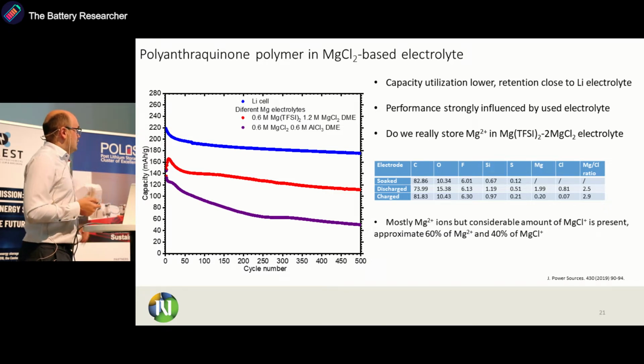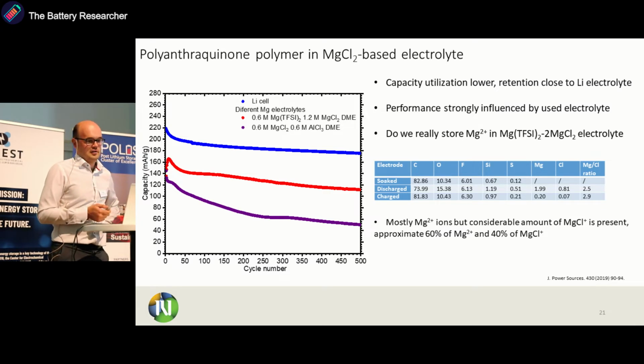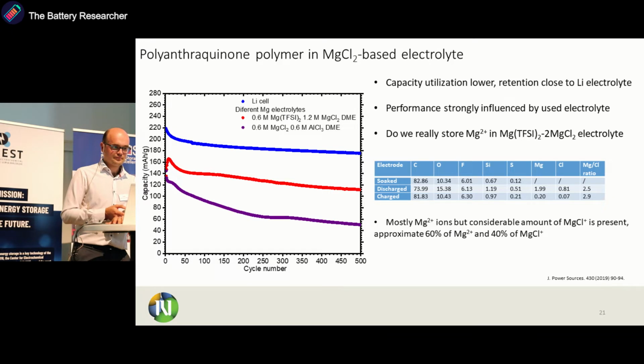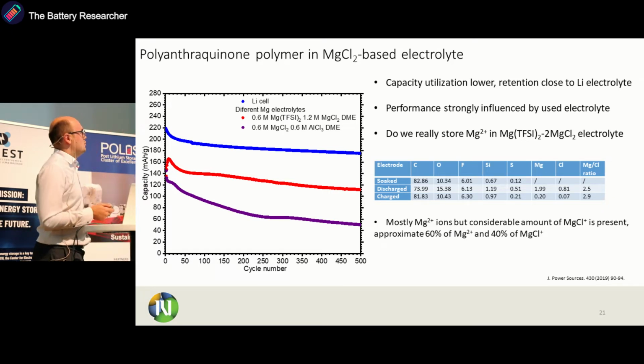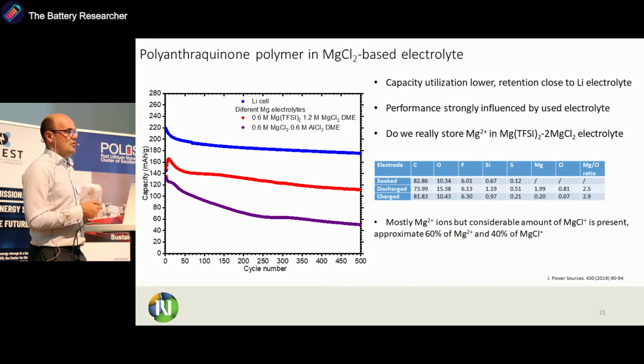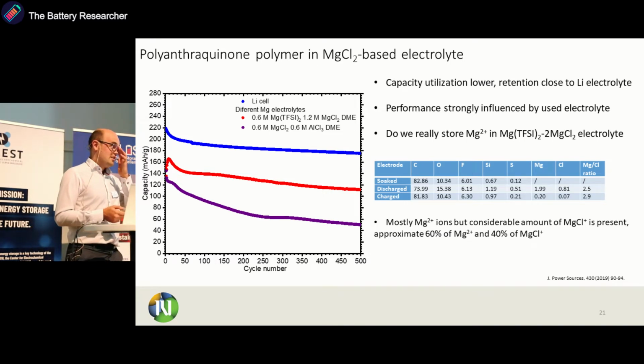We can also cycle it for quite some time, so we can achieve 500 cycles, which is quite good, and we still have 100 milliamp hours per gram of capacity, which is, let's say, not perfect, but quite good for magnesium. But then the question comes, what do we actually store inside? Are we storing magnesium 2+, or are we storing something else?